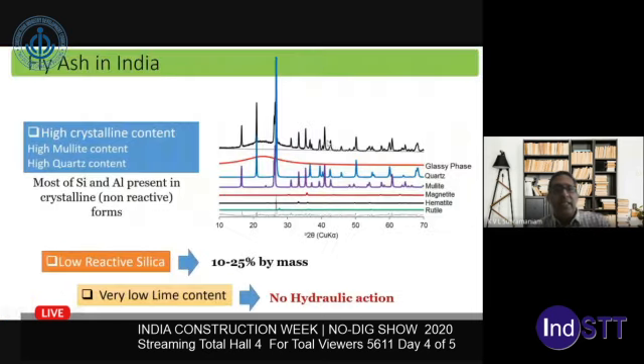So our next step was, through this characterization, we established from XRD-based analysis that most of the fly ash is basically the oxides, the silica and the alumina, locked in crystalline material. If you look at this XRD graph that I'm showing here, a lot of the fly ash is locked in crystalline content of quartz and mullite. Quartz is sand, which is very unreactive. So a large percentage of the fly ash is locked up in these unreactive forms.